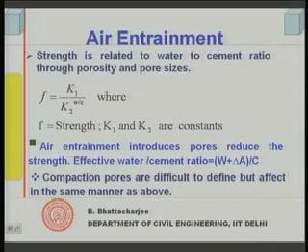Compaction pores will also behave exactly in the same manner, because they are also pores, but they are much larger size pores, and it is difficult to define what compaction pores should look like. They can be anything. Honeycombs are very weak points. If air remains in the concrete system and you have not been able to effectively drive it out during compaction, it will reduce the strength. There is no way around this, the only thing is to make proper compaction and make sure the air content of the concrete is taken care of in mix design. So, that is what it is.